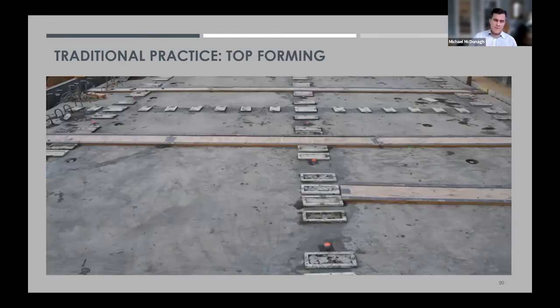I kind of skipped a step here, but obviously once the UHPC is mixed, you will place it in the connections. This photo shows a deck panel connection job. But whether it's deck panels or side-by-side box beams, typically your top surface is not level. Therefore, you would typically top form in order to keep the UHPC from flowing out the lower end because of its self-consolidating nature.